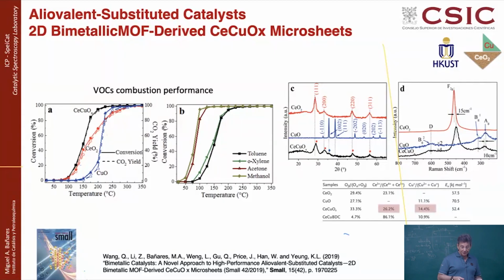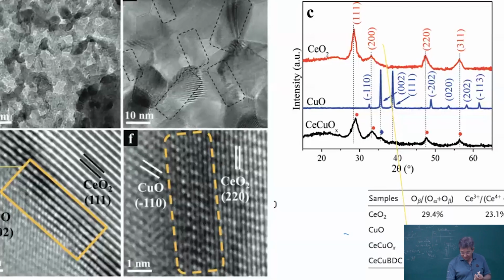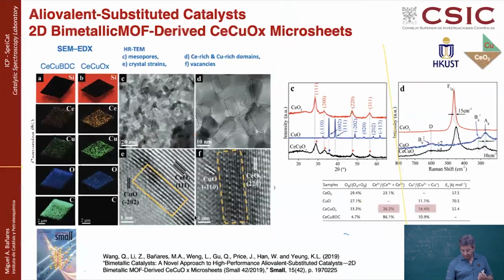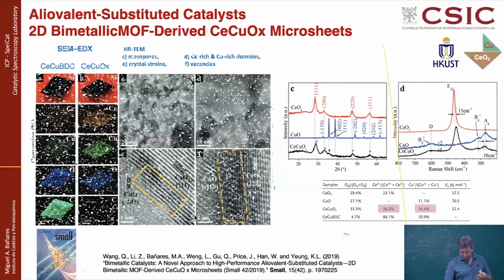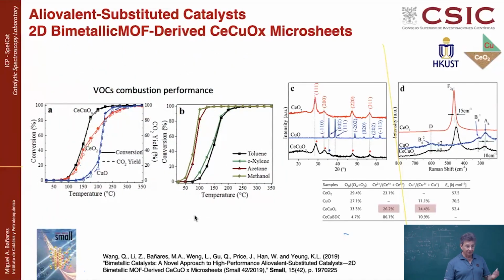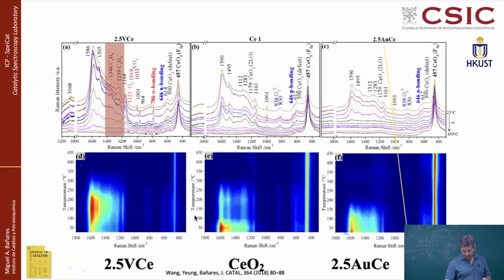The performance of this material was tested not only for toluene, but also for other volatile organics like xylene, acetone, and methanol. And the nice thing is it behaves well for toluene, but also for xylene, acetone, or methanol, which are other representative volatile organic contaminants.